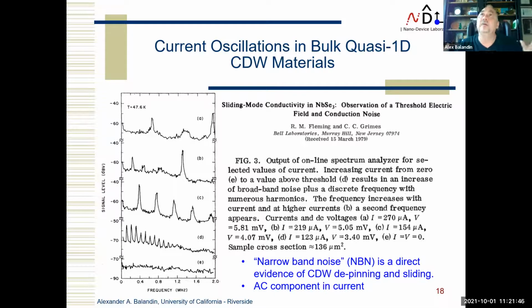But the problem, including from Bell Labs, was that this is all temperature things. Most of these materials, which revealed this charge density wave effects, required cooling them down to temperatures below 200 Kelvin. At the same time, you can make a beautiful oscillator. It's just a piece of material, a two-terminal device. You apply bias, and then you have these peaks at megahertz, called narrowband noise, which is not a correct term because it's an actual signal.